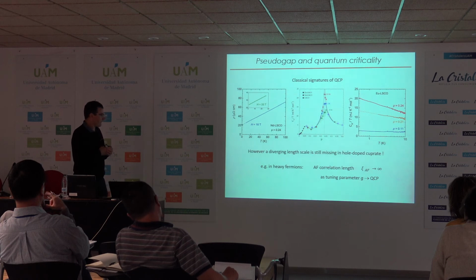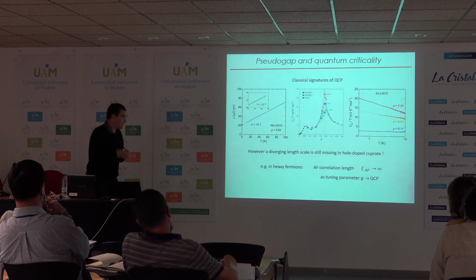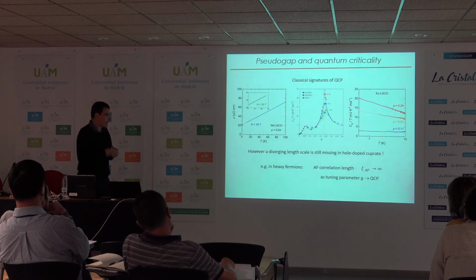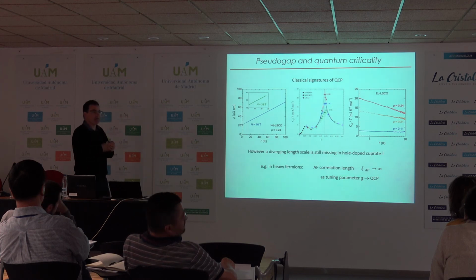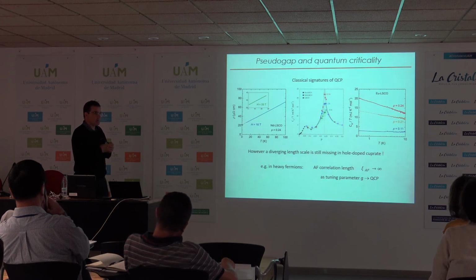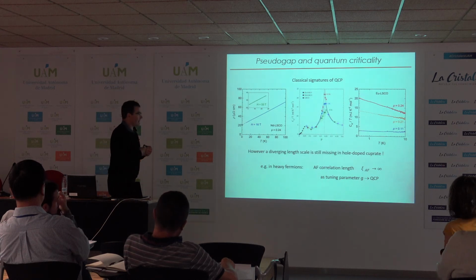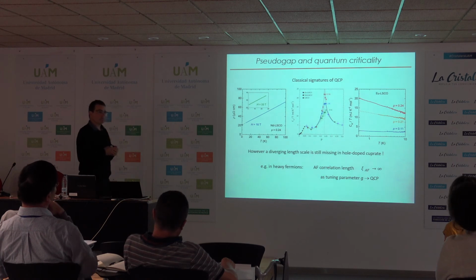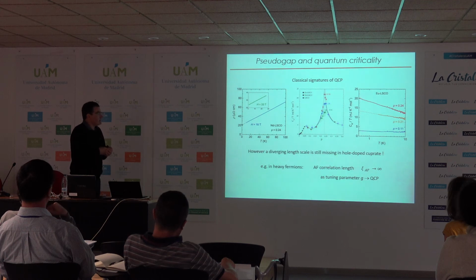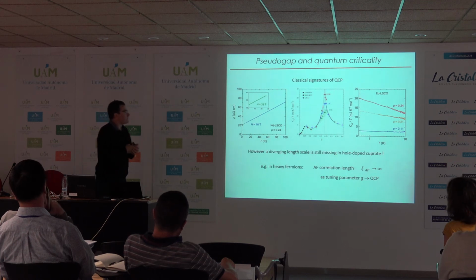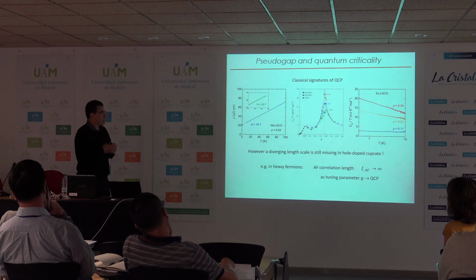The best example, of course, is the heavy fermion system, where the antiferromagnetic correlation length diverges at the quantum critical point. I mean, the 21% data could well peel off and go to a constant value, because the dashed lines, I suspect, are not data. No, they are not data. But my worry was that when I do see logarithmic behavior at higher temperatures, the coefficient is a different one. Yeah. So where can this quantum critical behavior come from?